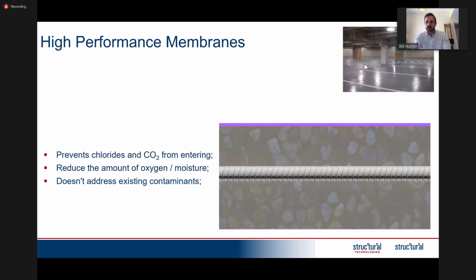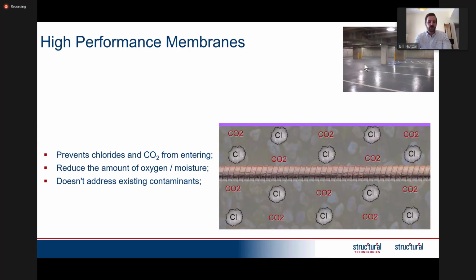A better solution for corrosion control can be high-performance membranes. If you have a high-performance membrane on your structure, yes, it can prevent chlorides and carbonation from getting in. It can prevent water from getting in, but it doesn't address existing contaminants. So this is where it's really important to maintain coating. A lot of the buildings we work on in Dubai are less than 10 years old, and we go into them and see the car park coatings have deteriorated. If you have a new structure, it's always good to maintain these protective coatings to prevent that contamination from occurring. Because once the contamination occurs, it's very challenging to address it.